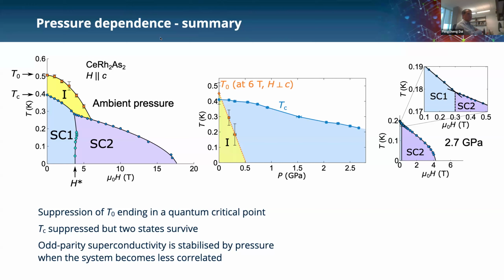Yeah, and just to follow up on this from experiment, we don't have lots of information on the gap structure yet. We have done thermal conductivity measurements, but on the very first generation samples, and there the signal is not clear. And we know from specific heat that the zero temperature extrapolated gamma term goes down with crystal quality, so we still think we cannot really analyze the temperature dependence. And then from μSR measurements, this is unpublished work, but Sung-Jung has presented it before, there seems to be a full gap.